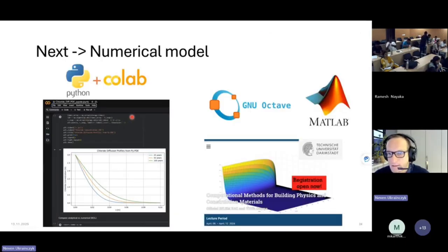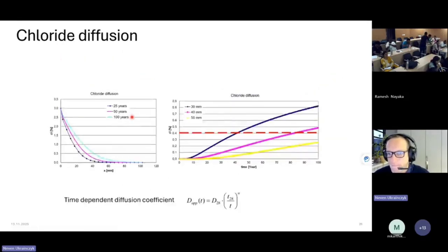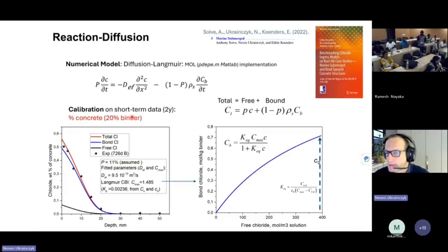So you will see some examples later in Python. I think this part I will explain later. Yeah, this is a reaction diffusion model. If you want to explicitly model the reaction, you should take it away from the apparent diffusion coefficient. Then you have your real effective diffusion coefficient, and you have your reaction term. And this is, again, the change of the bound chloride. So this is the binding rate. We have the 1 minus porosity and the density, because it depends on how you define it; here it is in mole per cubic meter of solution. And then this is the binding isotherm. With this model you can predict the total chlorides and also the free chlorides. The free chlorides are here. Those are the bound chlorides, somewhere there is a very high amount of binding, and you have the free chlorides.